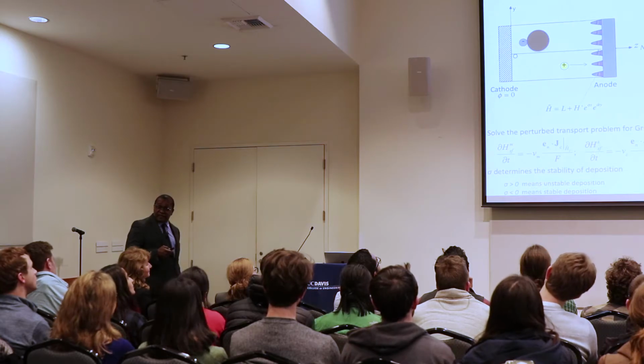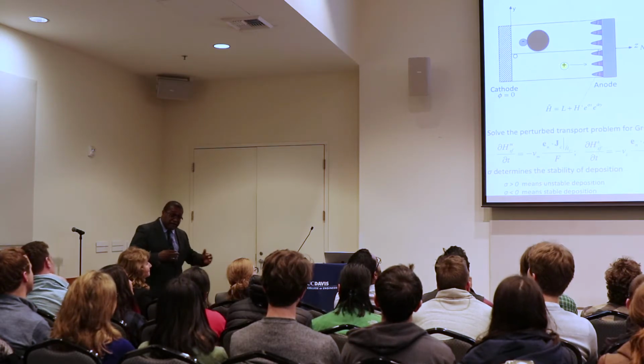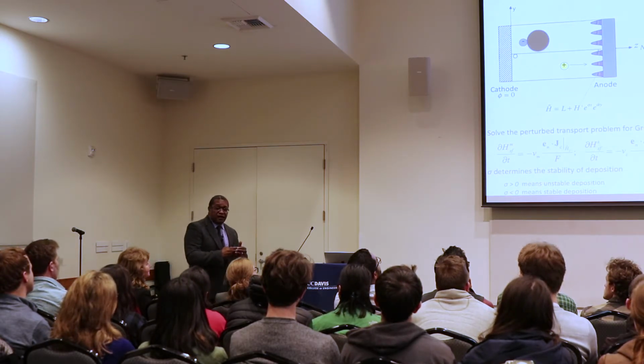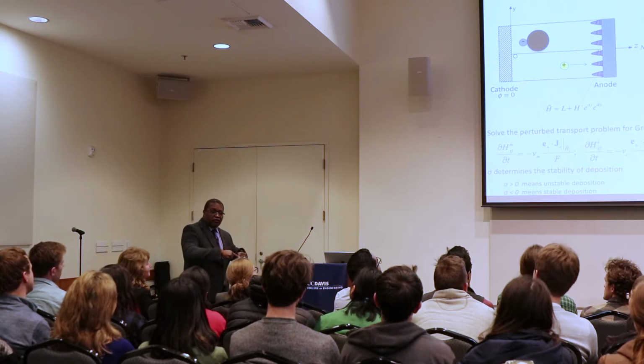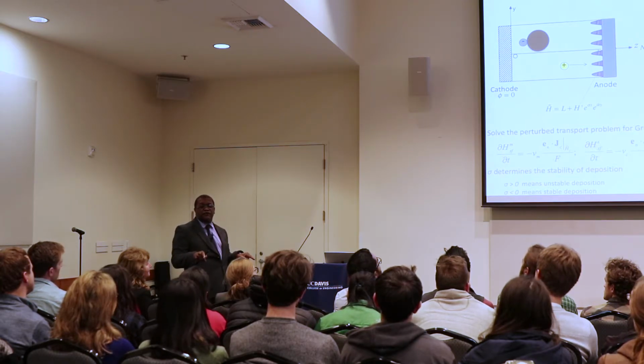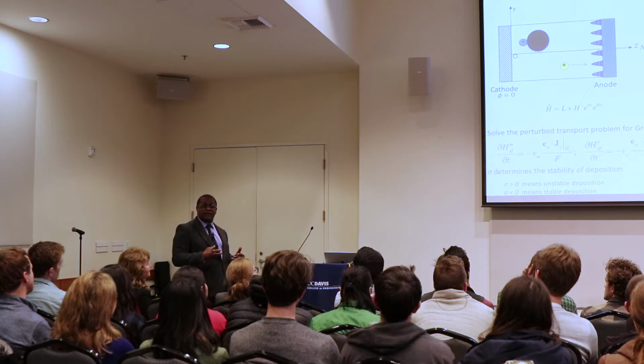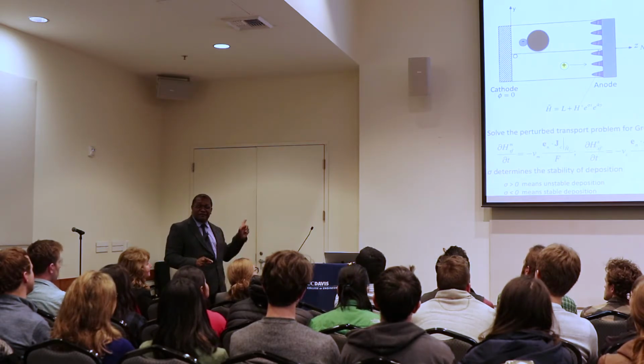Now it's obviously stabilizing, right? Because it's saying that the faster and bigger these bumps are, the greater the compression, the greater the driving force for things to move away from the bump. So the end result is that the more aggressive the growth is, the more distributed this mechanism makes it.